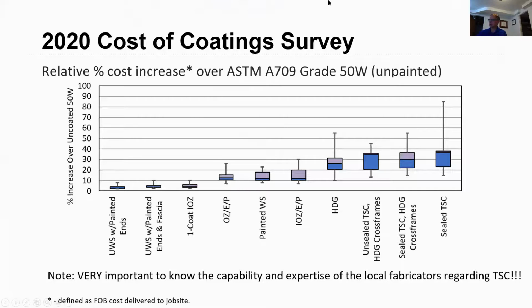So I'm going to use my cursor here, if I can find it. There it is. And these three systems over here, various variations of weathering steel and single coat IOZ, tend to be about a 6 to maybe 8% increase over weathering steel. Our typical painted systems tend to be about 10 to 20% more, and then hot dip galvanizing and thermal spray tend to be about 20 to 30% more. But this is very regionalized.